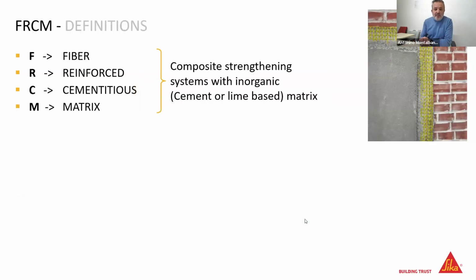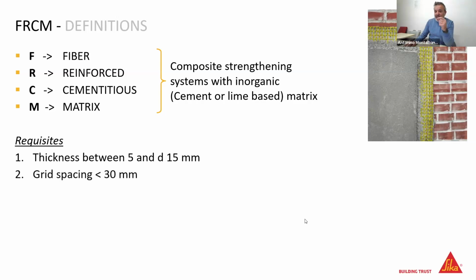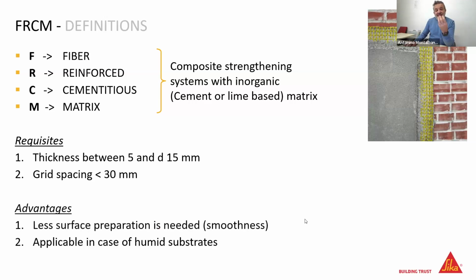So I will give you a quick overview on the FRCM, where the concept is the same, a composite material, but instead of using an organic matrix, in this case we use an inorganic matrix that can be cement or lime-based. The systems are thicker than the classic FRP, with a thickness that can go between 5 and 15 millimeters, and normally we use glass fiber or carbon fiber or sometimes basalt fibers with a spacing that is lower than 30 millimeters. So we use dense grids.